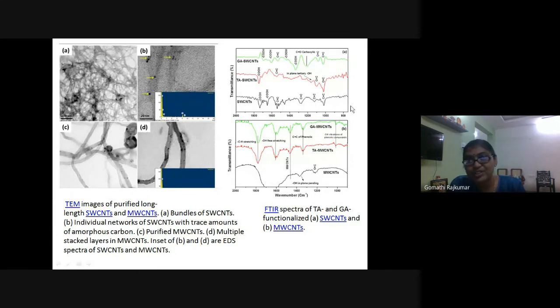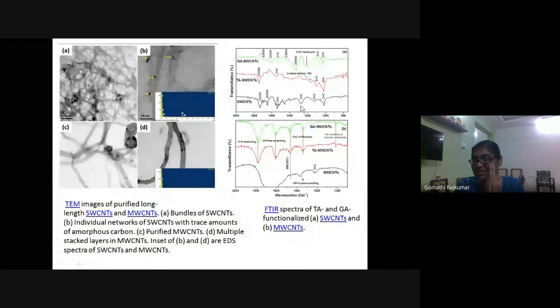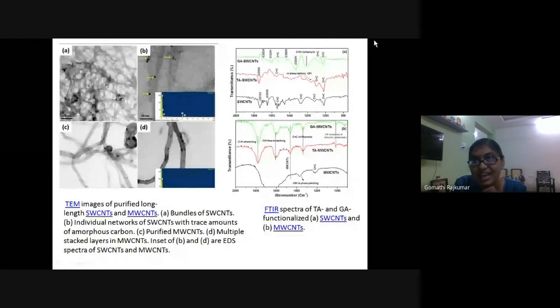Now here you could see the FTIR spectra. Now what we did was we mixed this with tannic acid, okay, with tannic acid. And here you could see that these carbon nanotubes were highly carbon, and you could see nothing more than carbon. See, the peaks here could show you that all these are carbon. And here, when it is coated with the tannic acid and with the gallic acid, you could see the peaks of all these phenolic compounds being present.